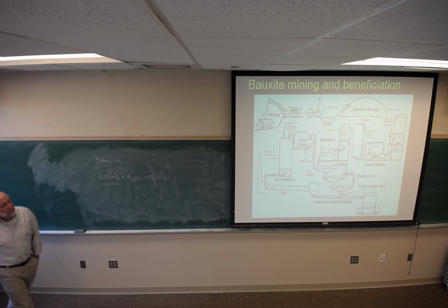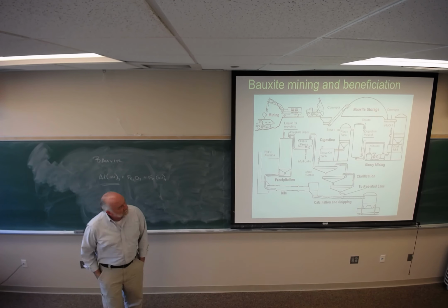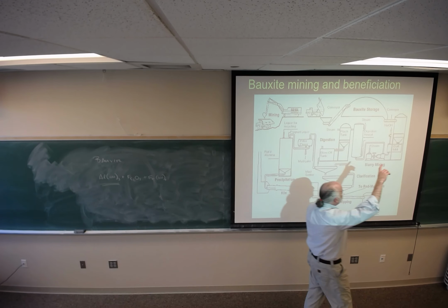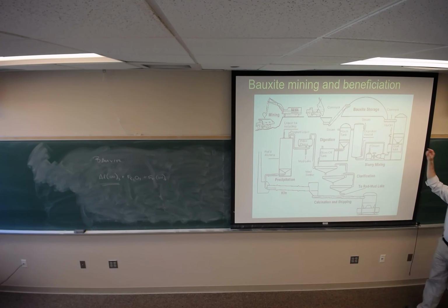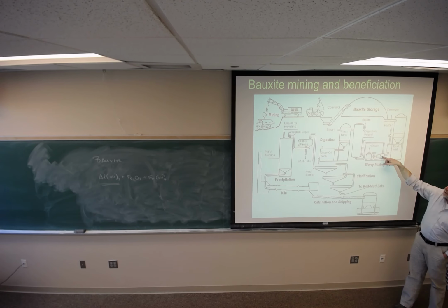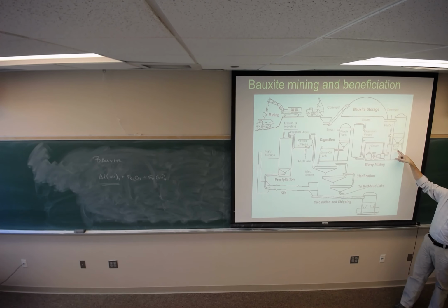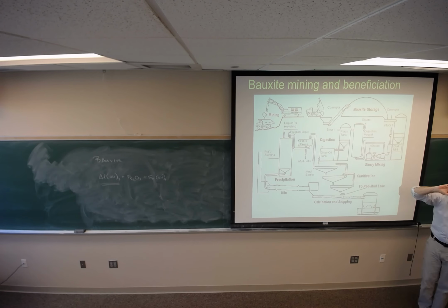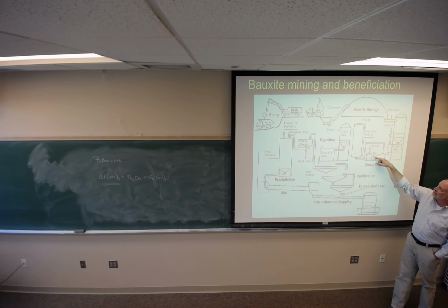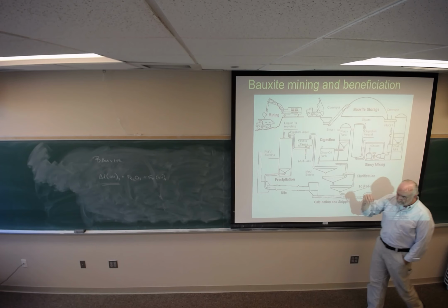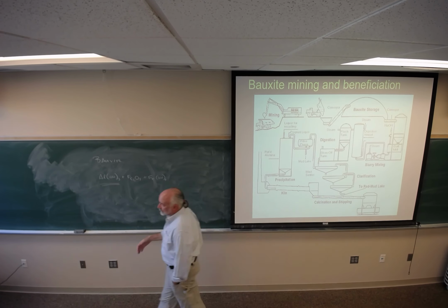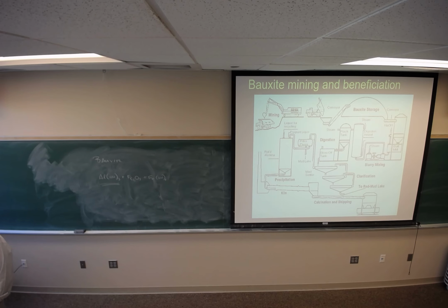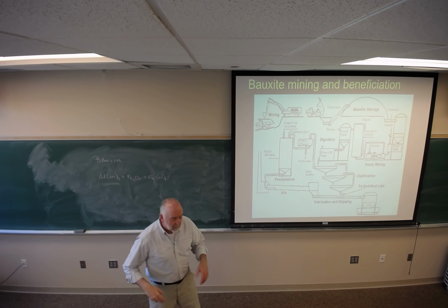Okay, so you mine the bauxite. It gets stored. It goes onto a conveyor. And then here it gets milled to give us a size that will react reasonably. It comes in. It gets heated with steam. Sodium hydroxide is introduced to the ball mill. So you end up with sodium hydroxide in contact with bauxite. And then it comes into a process and steam is injected to heat the system, because as you drive the temperature up, the aluminum dissolution rate goes up dramatically. Okay? So by warming the system, you can dissolve the aluminum hydroxide out much more rapidly. That's called a digestion vessel, so that's where the material is actually dissolved.